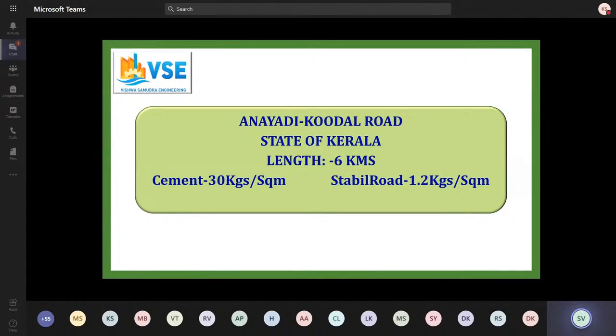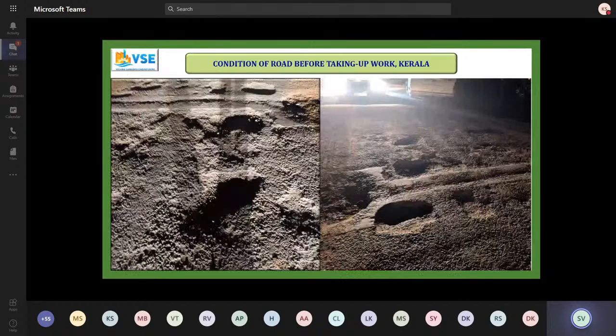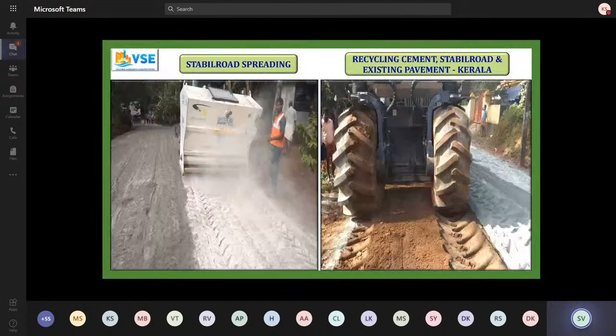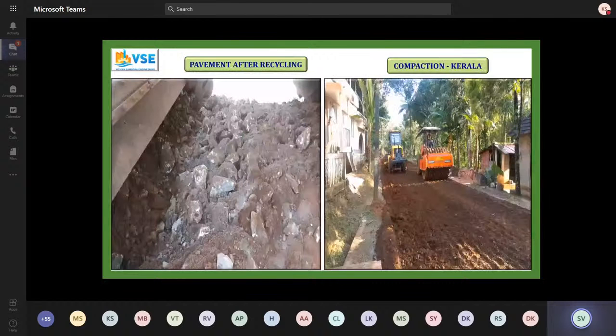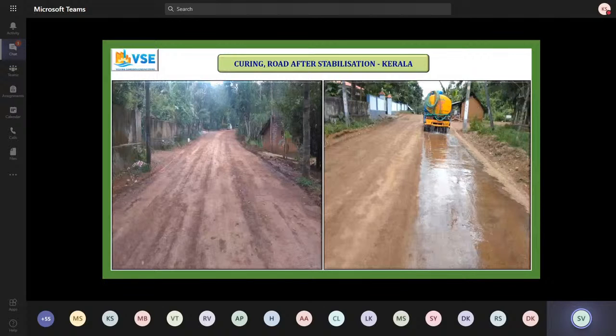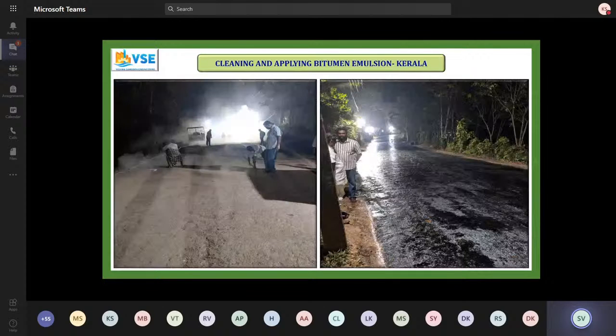Like I said, we don't scarify it. We don't do as it is. We spread cement on top of it, we spread the additive, recycle it, and then we compact and give 3 days of curing. This is how the surface looks after 3 days. It's very strong, if you look at it.